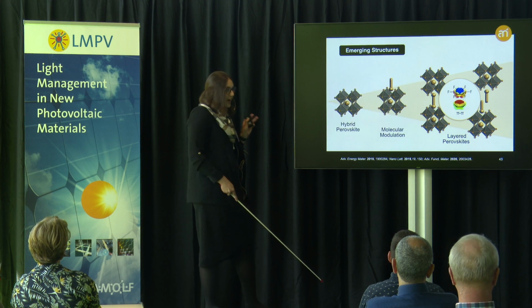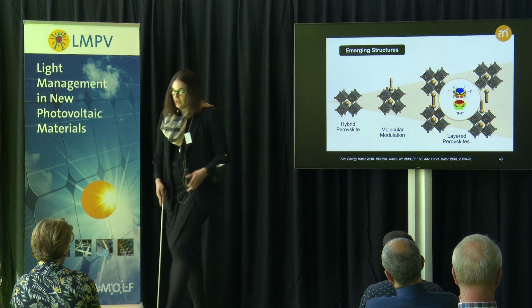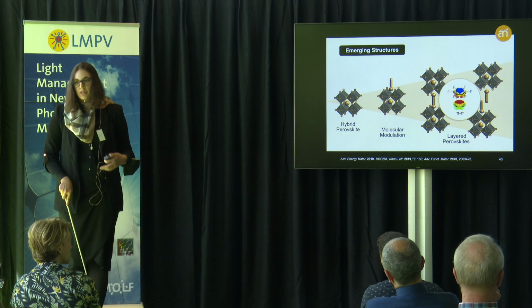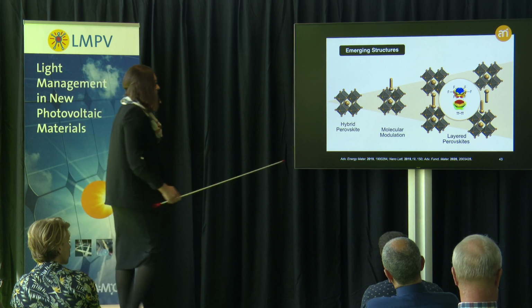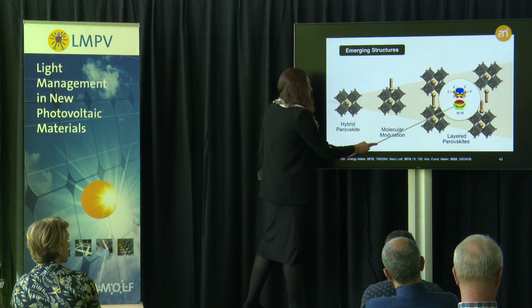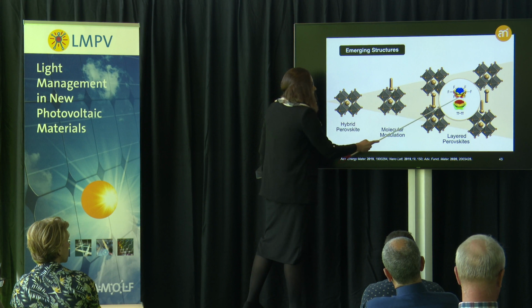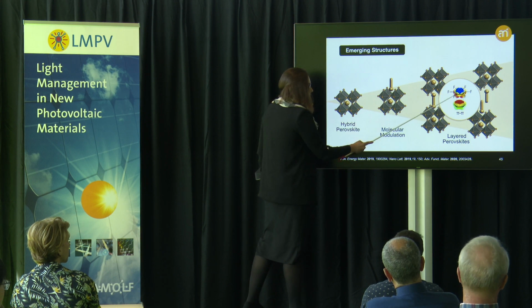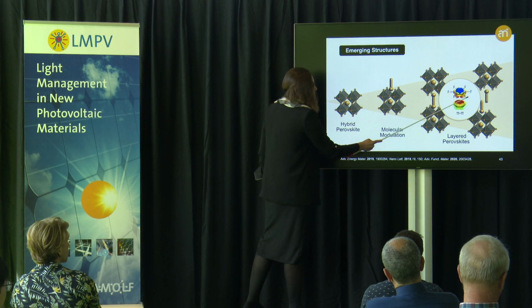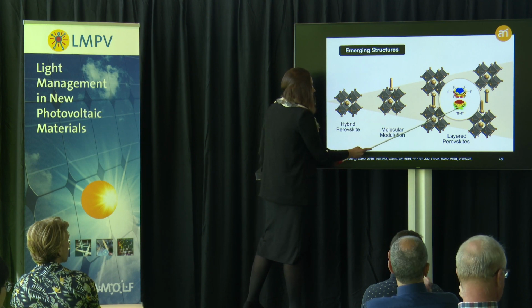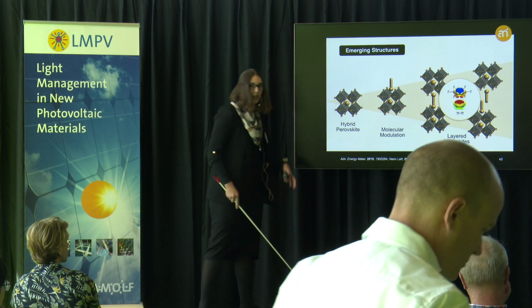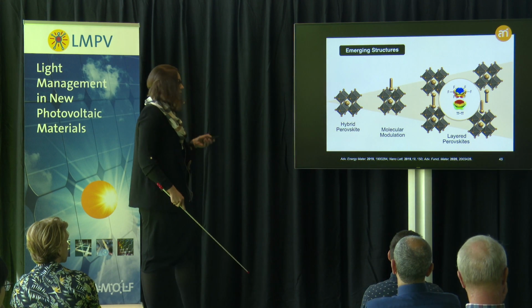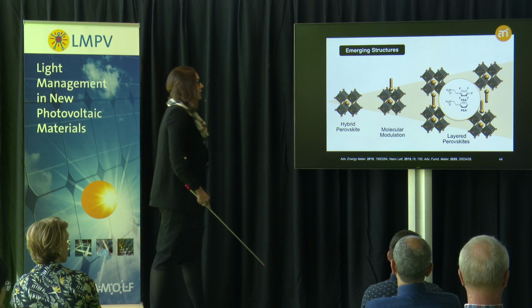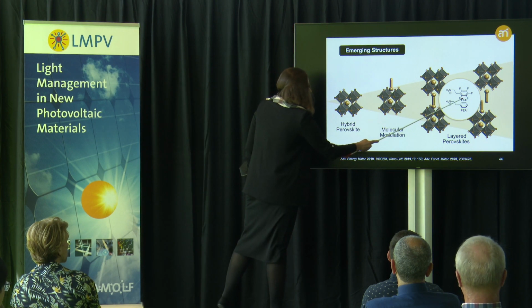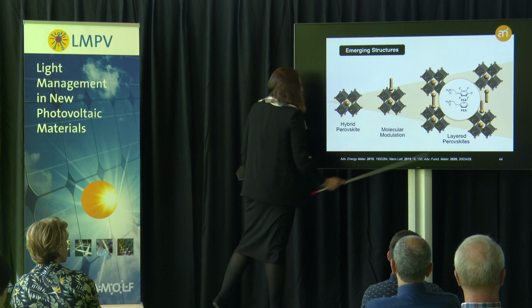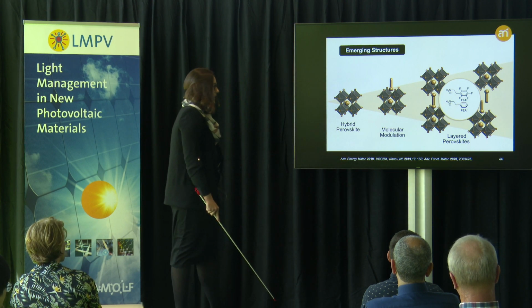Especially by relying on these pi-based interactions that I highlight as we've been hoping to also relate to them when it comes to controlling the ionic properties of these systems, and which essentially refer to changing the polarity of the typical aromatic ring, inverting the polarity in order to strengthen these interactions and make accessible more of these parallel interactions that rigidify this organic layer and further stabilize the resulting systems. And for this purpose, we relied on two different model systems that are illustrated here. So these typical phenylethyl ammonium and the perfluoroarene-based systems, both of which form well-defined perovskite phases, and which were, in